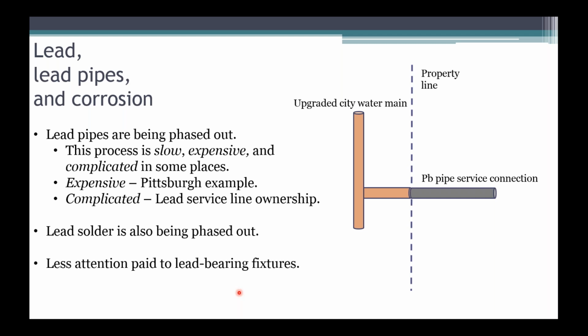Additional complications arise when service line ownership is considered. Even when the city replaces its part of the service line, it's possible that there will be part of the service line that's owned by the homeowner, or plumbing within the household that contains lead as well. Okay, and so fixing that part of the problem is also slow and complicated, because you're really counting on the homeowner to realize that they have lead plumbing, to realize that it's a problem, and then to spend their own money to fix it. Okay, and so that can also slow things down quite a bit, and it presents a different kind of problem than the city upgrading its own distribution lines.